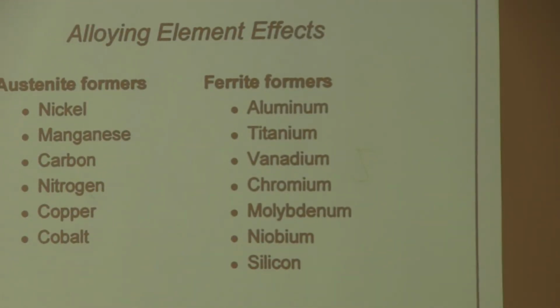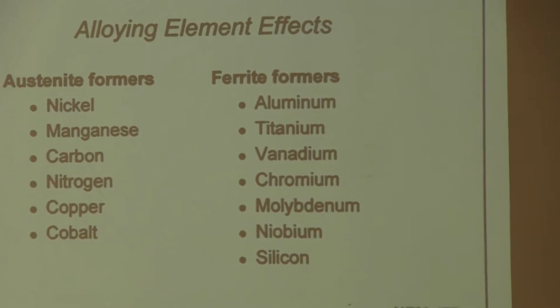So I wanted to talk then a little bit about some of the different alloying elements that we end up putting in stainless steels. And they're broken down into two categories. One is the austenite formers, which promote the formation of austenite, and the ferrite formers, which promote the formation of ferrite, which can then solidify as ferrite. Well, austenite formers actually end up being martensite, because when the austenite cools down, it can transform to martensite.